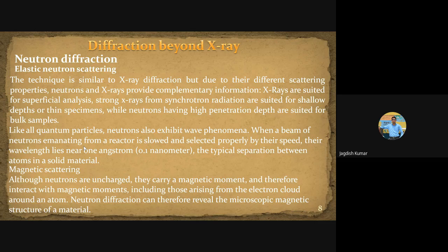If the crystal is non-magnetic and you employ neutrons and X-rays of exactly the same wavelength, then the X-ray and neutron diffraction patterns will be exactly the same, because there is no magnetism, hence both patterns will match. But in case there is some magnetic moment, suppose your crystal is antiferromagnetic, then there will be additional peaks in the neutron diffraction pattern, because there is an atomic periodicity, and then there will also be a periodicity of magnetic spins. So in an antiferromagnetic crystal, what do you have?